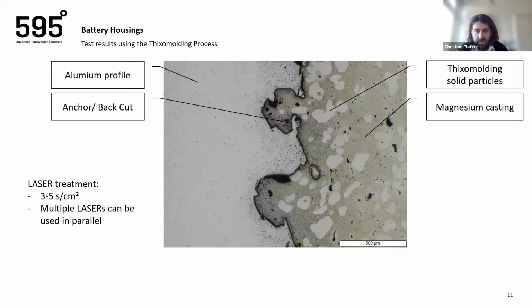And the result after some trials has been already quite satisfying. We have been able to provide a bonding that was media tight and also showed quite good peel adhesion, because it's not so easy to classify the bonding actually. The bonding that we are creating with this is not, the magnesium is not melting the aluminum when it's overmolding the aluminum. It's just flowing into the lasered structures, and those lasered structures are showing back cuts.